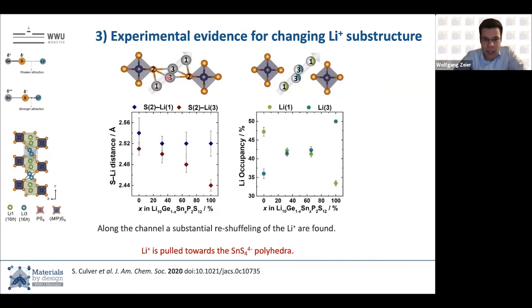The bond distance that changes is this one here, of the lithium 3 that is closer in distance to the sulfur 2. This bond distance decreases from germanium to tin, meaning that the more tin we have in there, the higher the charge density on the sulfur, the closer this lithium-sulfur distance becomes. And concurrently, we also see changes in the occupancies.